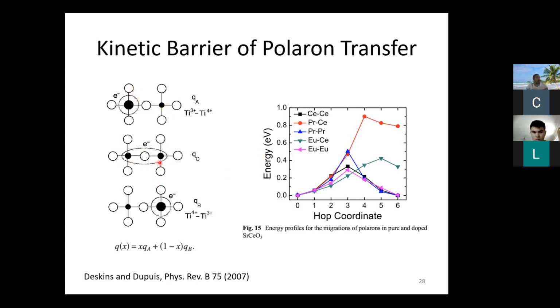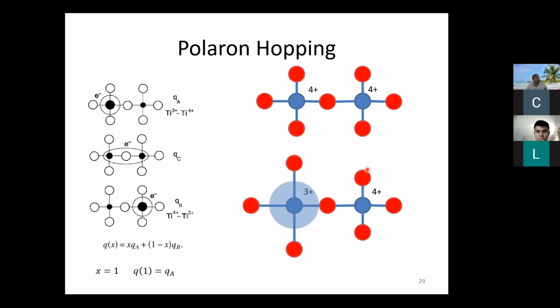And so if I capture an image at each position from my simulations, I can get this kind of barrier. From this barrier, I can then calculate migration barriers from the activation energy. And I could get conductivity if I know the particle number, which you can obtain from Hall estimates experimentally. So this is a diagram I drew up.